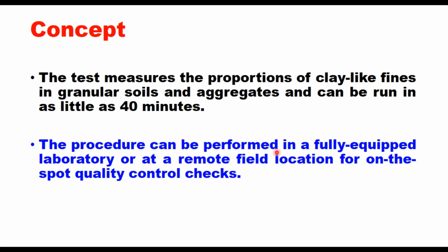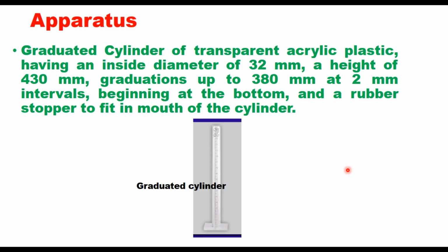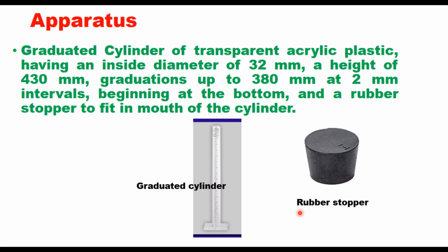The procedure can be performed in a fully equipped laboratory or at a remote field location for on-the-spot quality control checks. The apparatus required for conducting this test is a graduated cylinder of transparent acrylic plastic having an inside diameter of 32 mm, a height of 430 mm, and it is graduated up to 380 mm at 2 mm interval. These graduations start at the bottom, and it also requires a rubber stopper to fit in the mouth